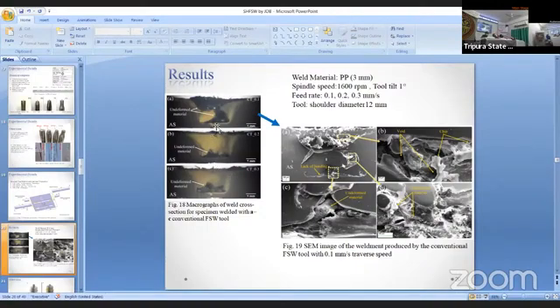For all the feed rates, it has been seen that undeformed materials are present, because the heat was not sufficient to deform the material, to plasticize the material fully. As you can also see in the SEM image, undeformed materials are present, and voids and chip formations are there. That is because of the lack of sufficient heat for the welding.